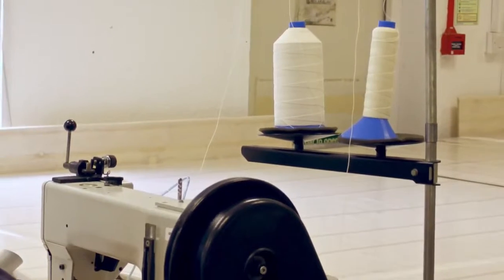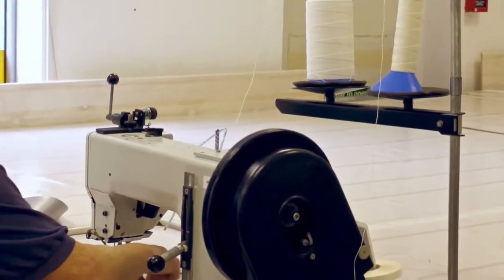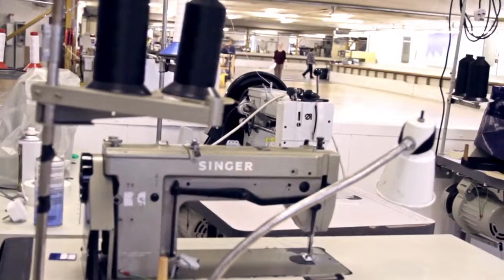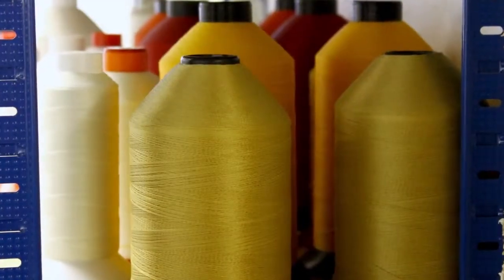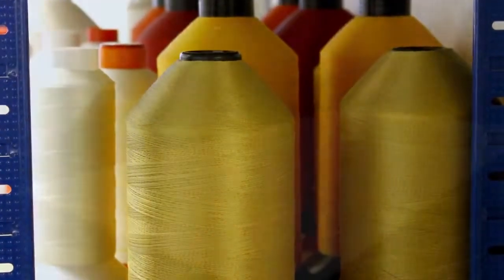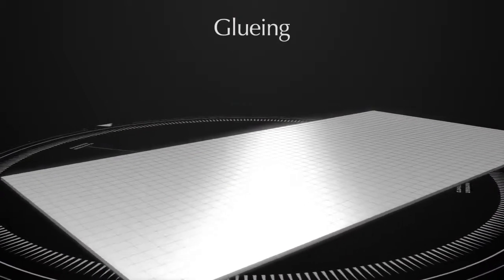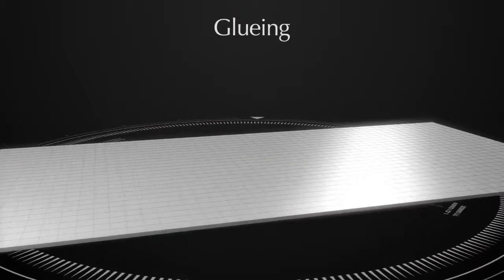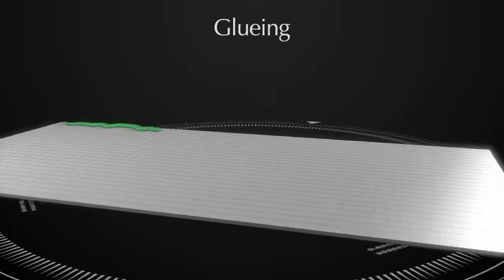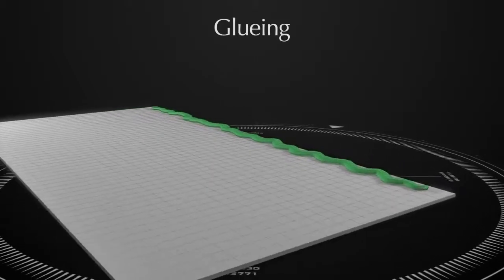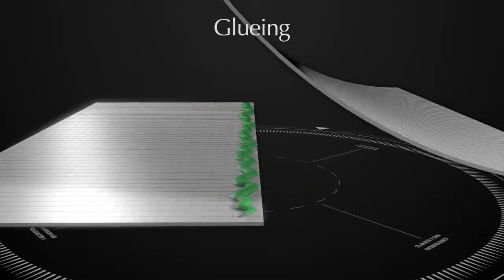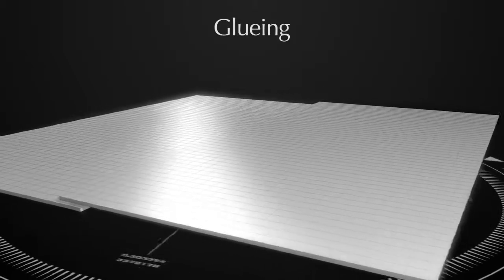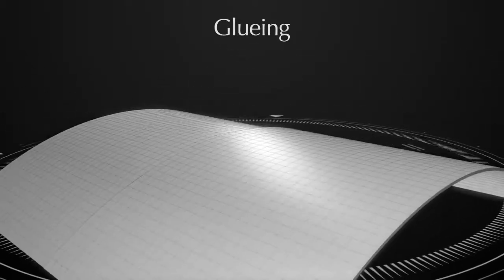Sewing is suitable for smaller projects, and for reinforcement patches on some larger membranes, we use industrial sewing machines and UV-stable thread to join the fabric layers to one another. For some applications and some types of fabric membrane, including silicone-coated glass cloth, welding or sewing are not an effective means of joining. Gluing using a high bond adhesive will provide a joint with adequate strength and durability.